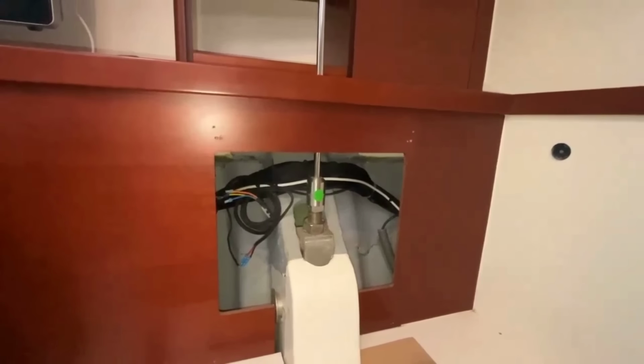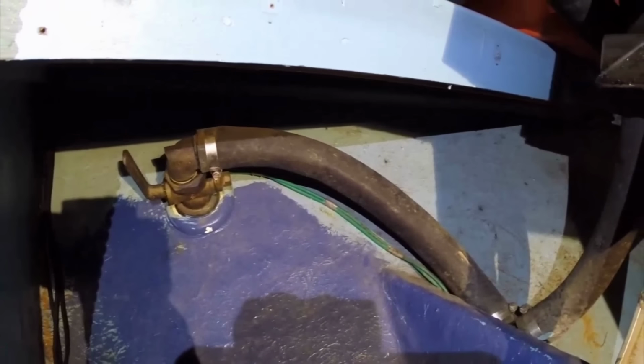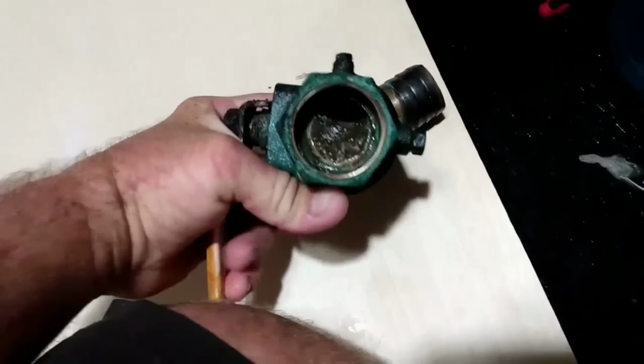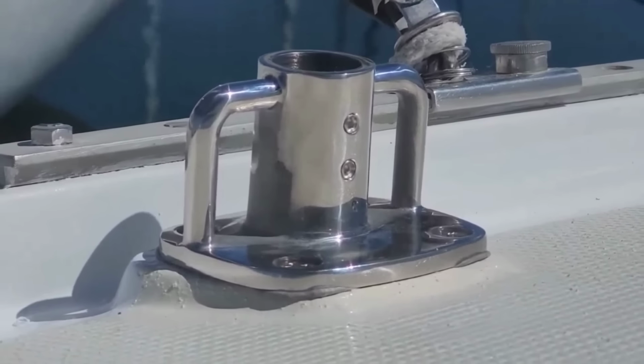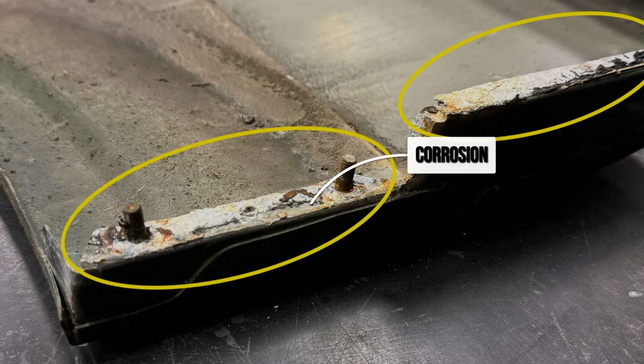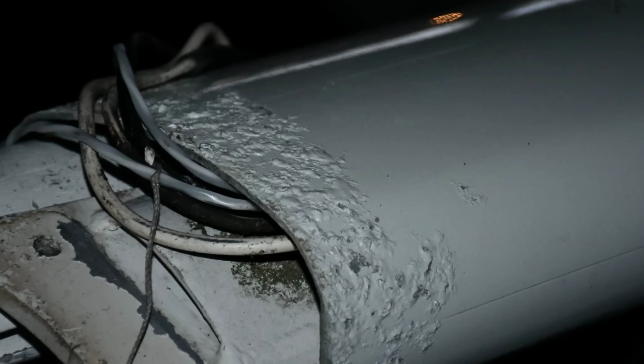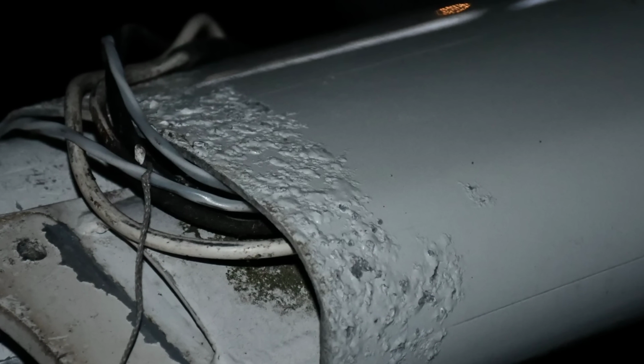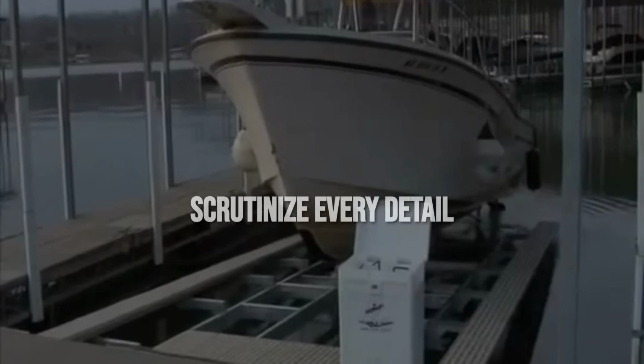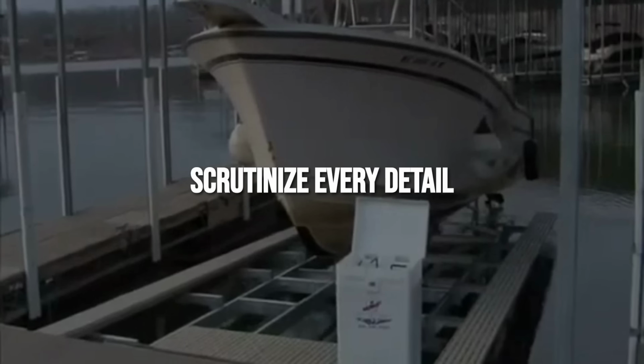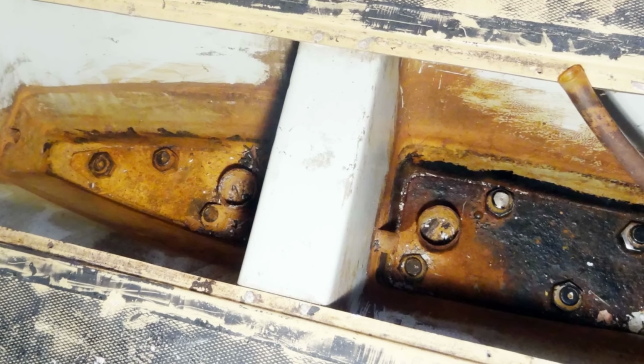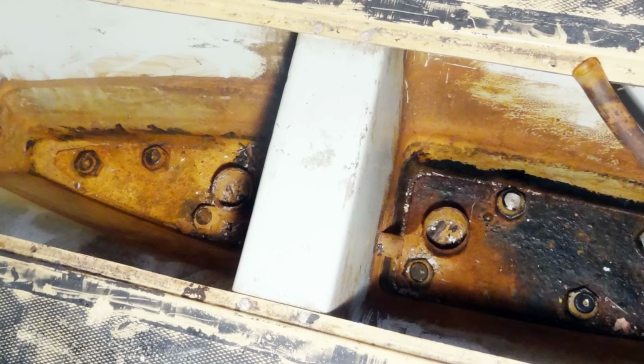Pull the bilge panel. Look at where the drain lines from every fish box and compartment actually terminate. If they go into the bilge instead of overboard, that is a chronic water introduction point that has been running since the day the boat was built. Check every aluminum component that contacts stainless steel hardware for powder coat bubbling at the joint. Bubbling means active galvanic corrosion is already working underneath the surface. Ask how the boat was stored. Dry storage on a lift between uses ages a hull at a fraction of the rate of a boat left in a saltwater slip. That single variable changes the expected condition of every component on the boat.